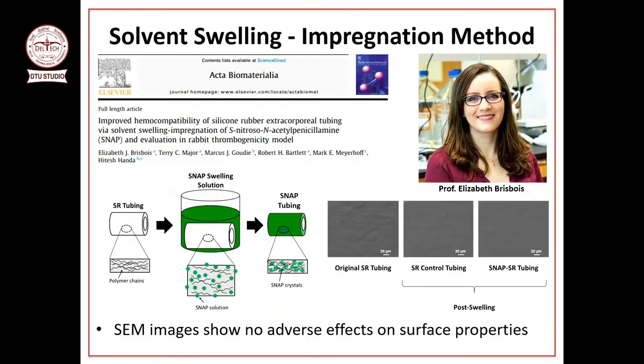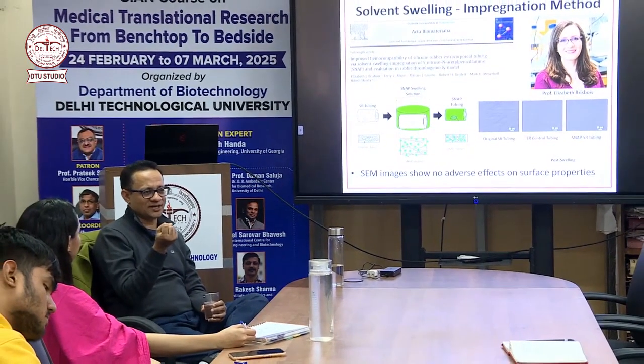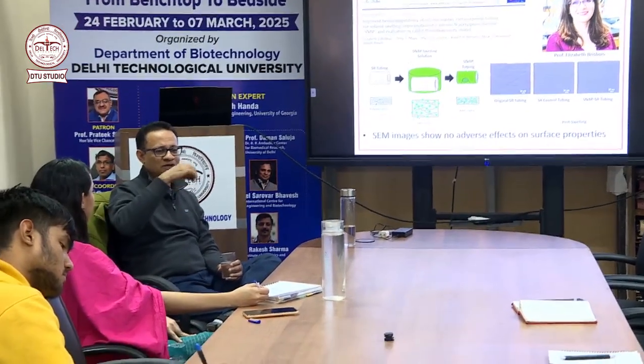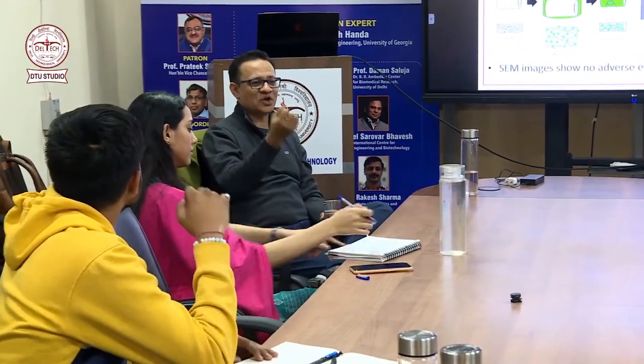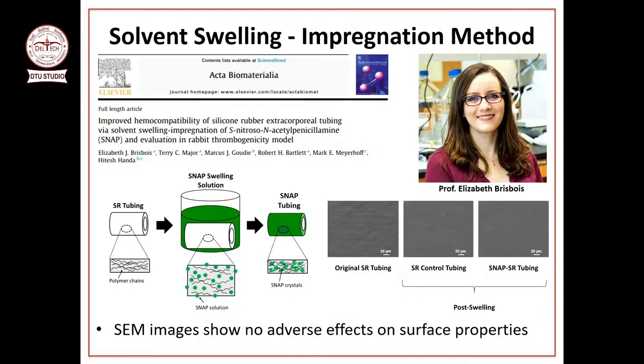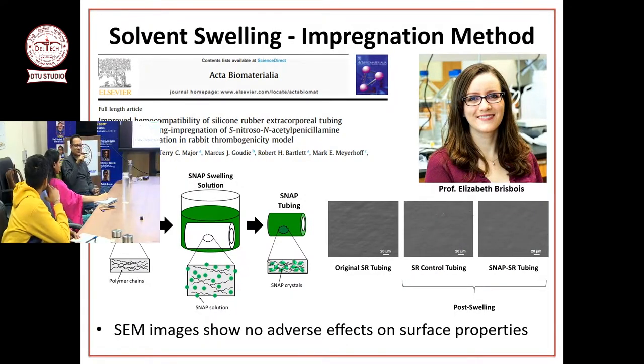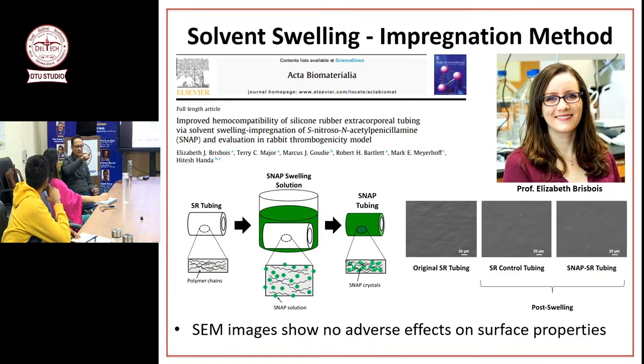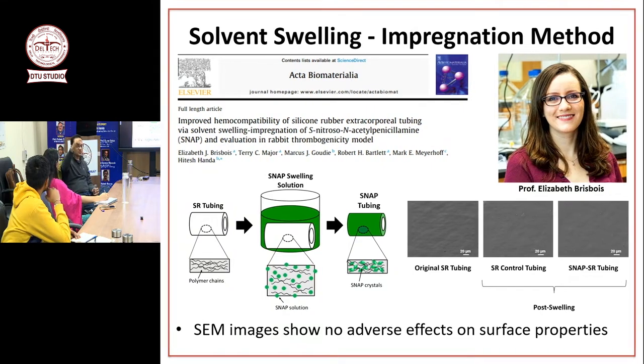So this paper was very good, in Acta Biomaterialia. What we showed here was that if we swell polymer tubings, so what we do is we have a solvent with NO donor dissolved in it. We take existing catheters or existing tubings and swell them in that solution for, let's say, 24 hours. The idea is that the solvent will take the NO donor molecule into the walls of the catheters. Take the catheter or tubing out, dry it overnight or 2 days or whatever with vacuum to make sure you get all the solvent out. Now all the solvent is gone, all the NO donor is inside the wall of the tubing, and now you have a NO releasing material ready without extruding, without making a film, and it's very uniformly distributed inside the wall of the tubing, and you have a NO releasing surface ready.